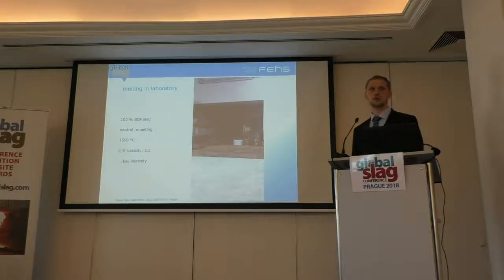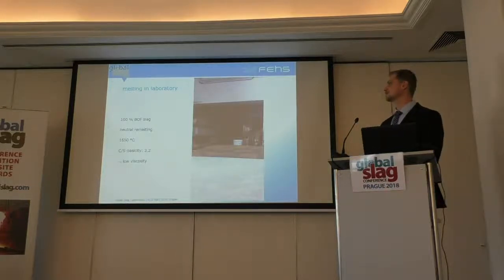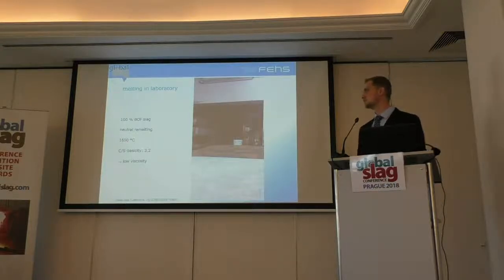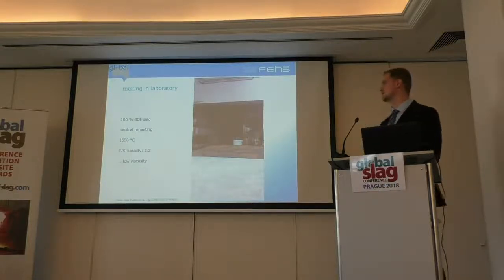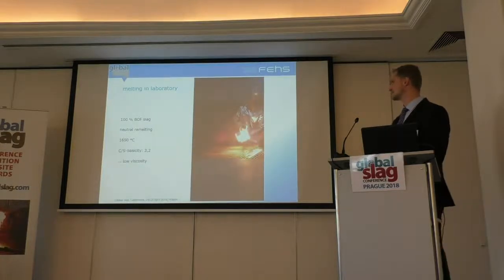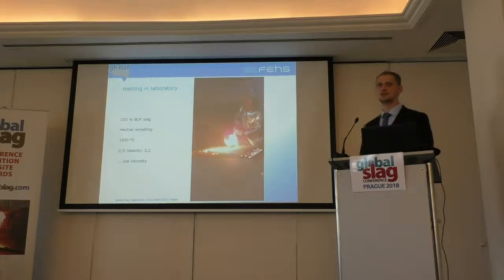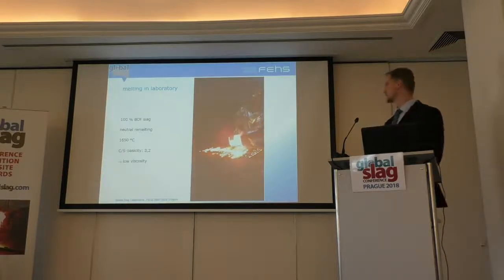First of all, as I told you, we can remelt slags under neutral conditions. Here, one video shows how it looks when we are remelting a BOF slag under neutral conditions at 1650 degrees and typically a basicity of 3.2. You see here, it's more or less like water, it's very, very liquid, no problem with the viscosity. So it's very good to handle this material.